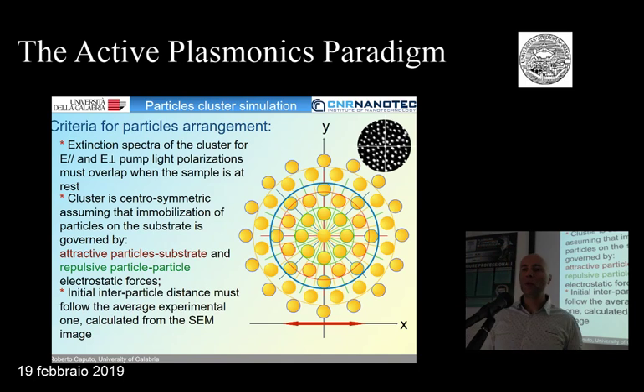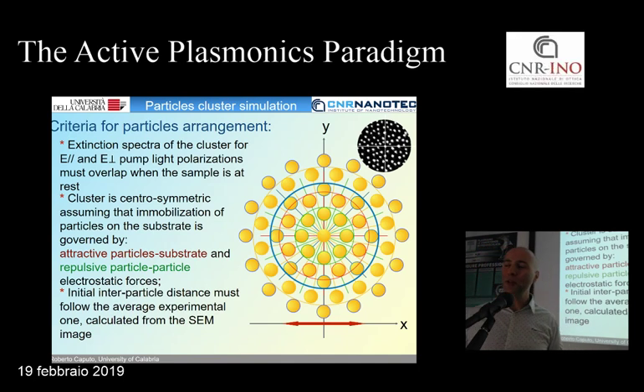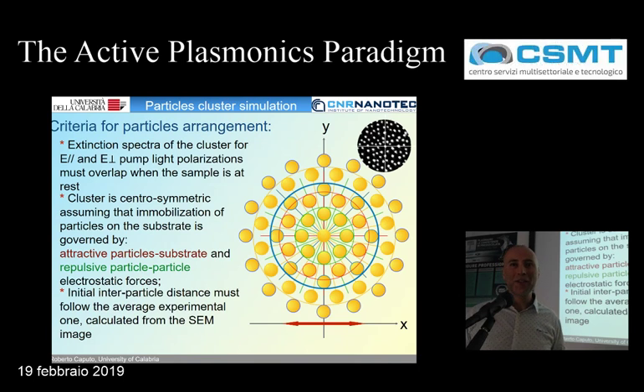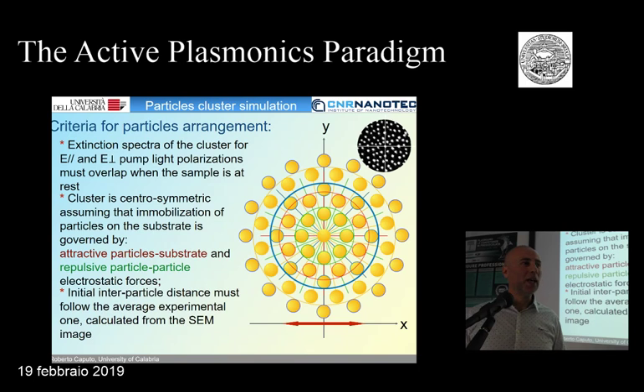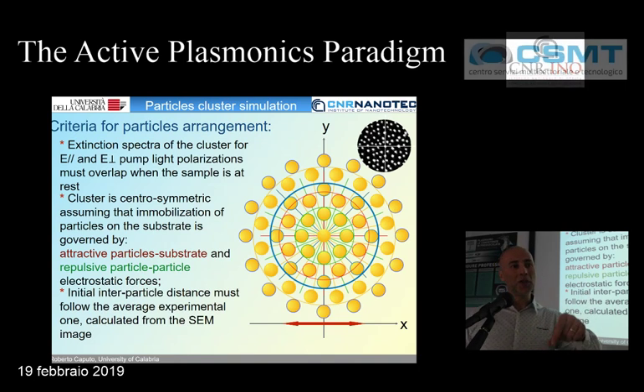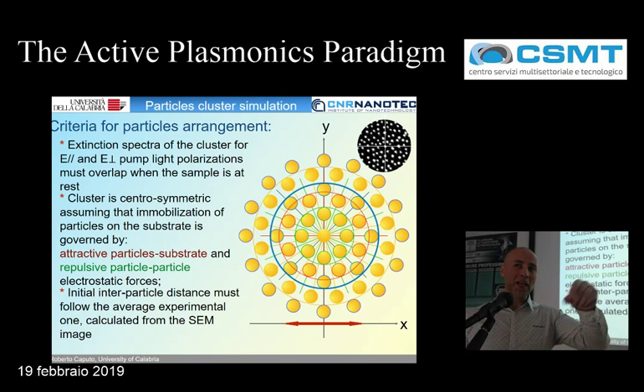So we wanted to model this system, and it was not very easy because we start from a homogeneous, a uniform distribution, but which is not regular. So studying a random distribution of particles by COMSOL was not ideal. And moreover, the next step is to abandon the uniform random distribution for something which is more ordered, because when it is ordered, you can engineer in some way the position of the hotspots and the places where the temperature will be higher when you apply your strain.